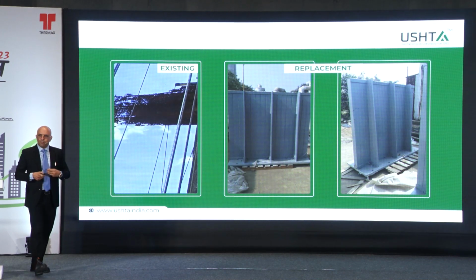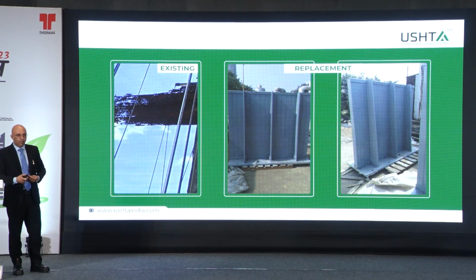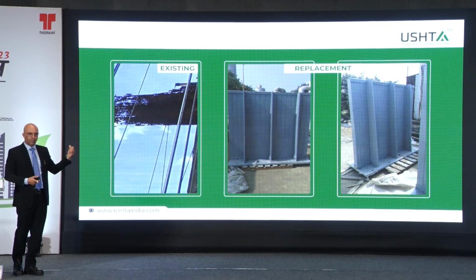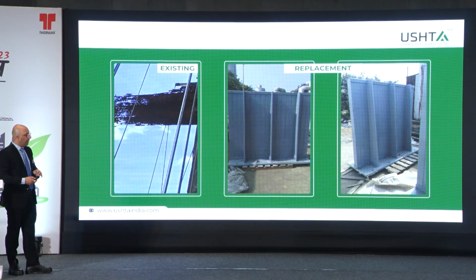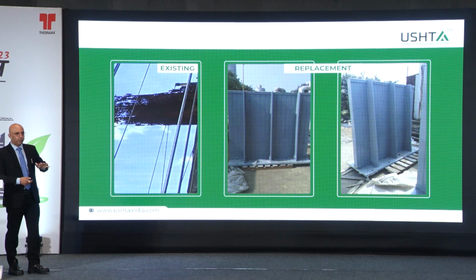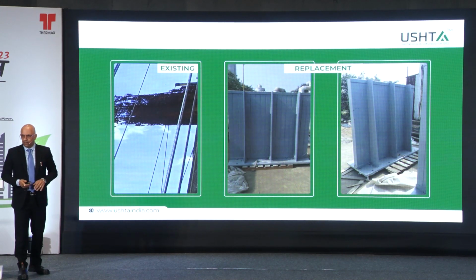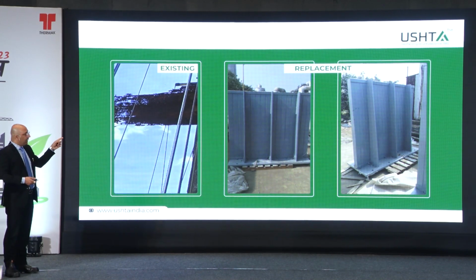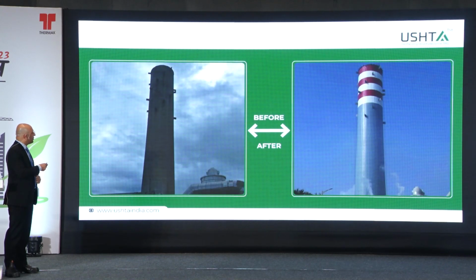These are sections made out of fiber which are lightweight in section but very sturdy, the weight to strength ratio is higher than that of steel. And there is no corrosion. So even if you don't paint it for another 15 years, it's fine. Because this painting is at 124 meter, and each size is 1.5 meter by 1.7 meter. So you can't have an access to this. And this is the structure before and after.